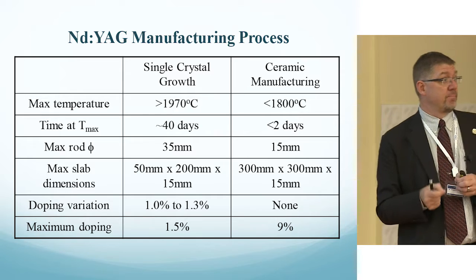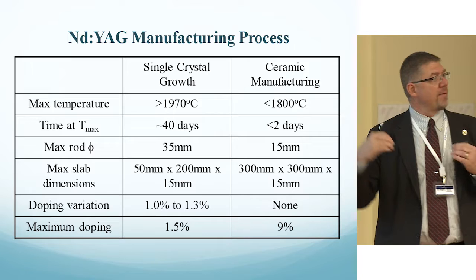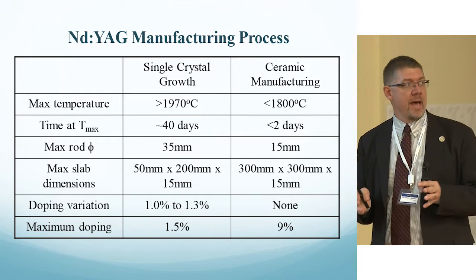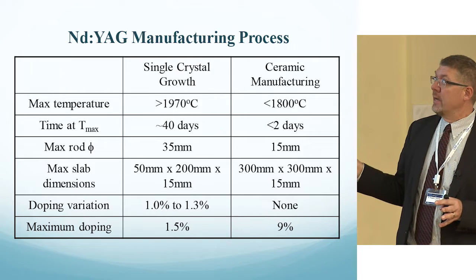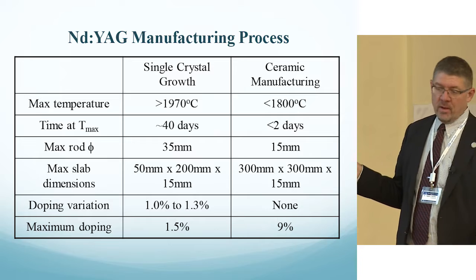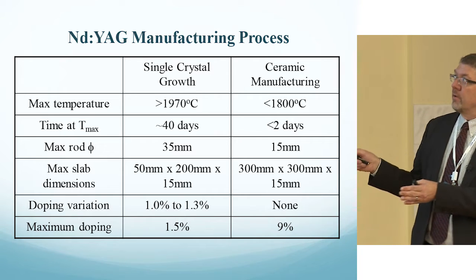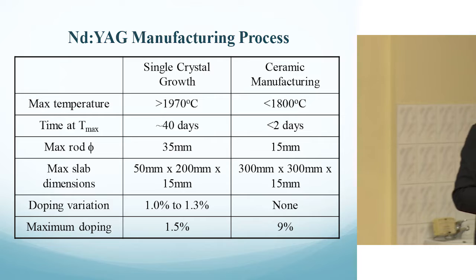Now there is a lot of chemical preparation that's not built in here, but it's about 5 days per large slab. So even at that point, if you add that in, it's a 7 day process, starting from the powders to the end of the material, versus 40, 41 days with single crystal growth.